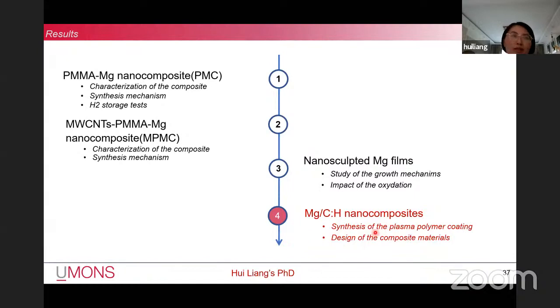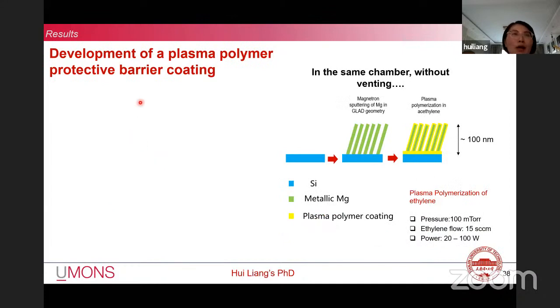The first part is the MgCH nanocomposite by a plasma-based approach, including synthesis of the plasma polymer coating and the design of the composite material. Develop a plasma polymer to protect Mg. In order to protect the MgC film, we develop a plasma polymer coating. A metal sputtering device is shown in the right picture. On the silicon substrate, argon is used as a sputtering gas to sputter Mg, and then plasma polyethylene is deposited on the surface of the nano-MgC film.